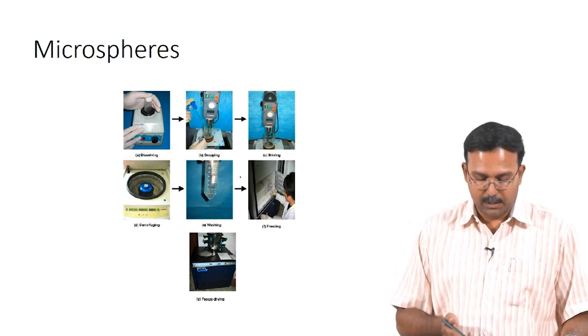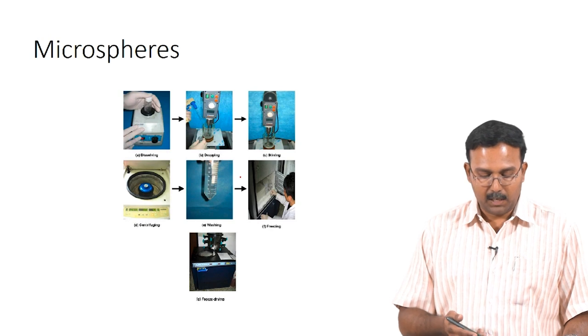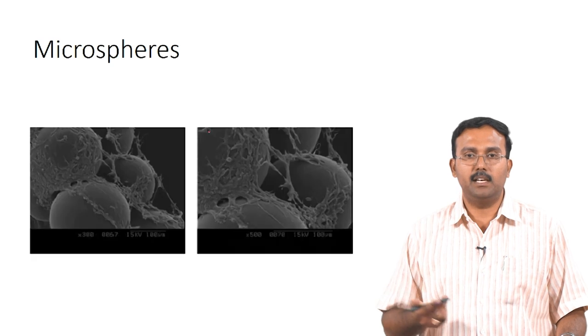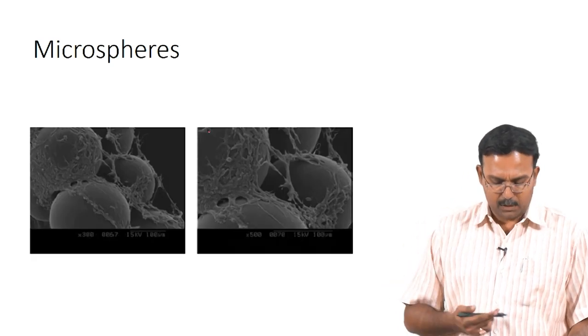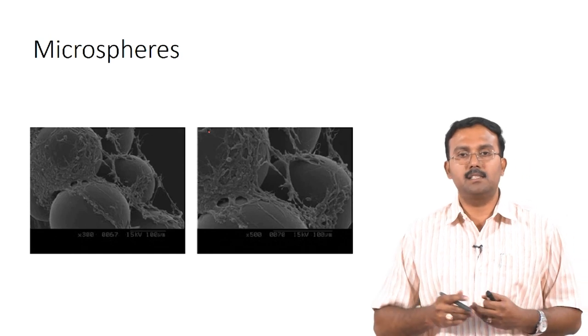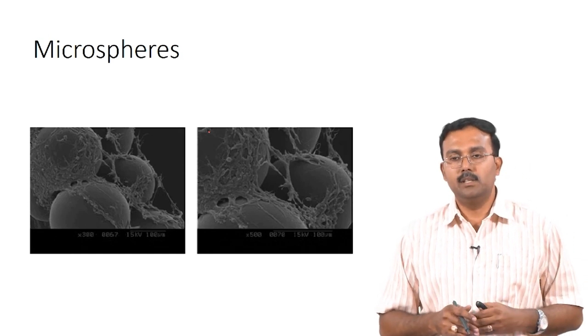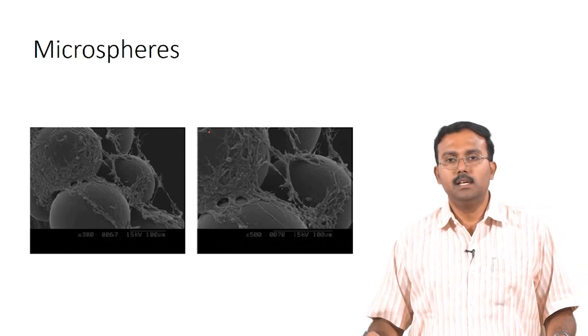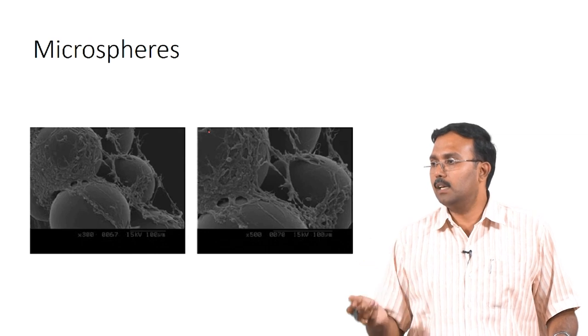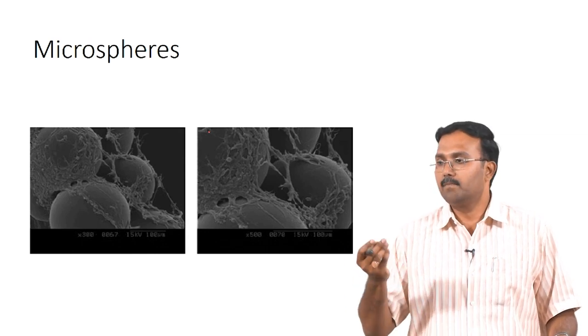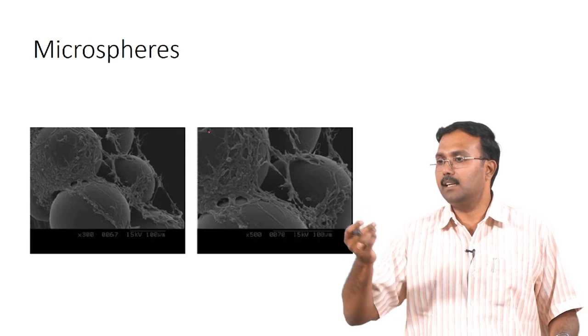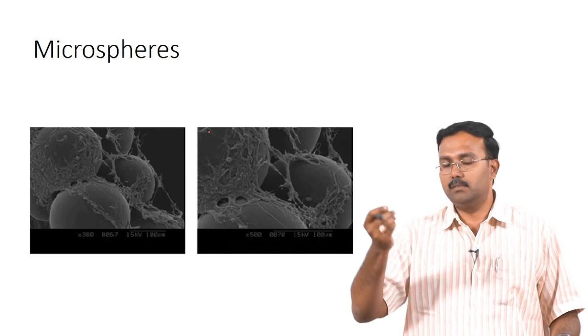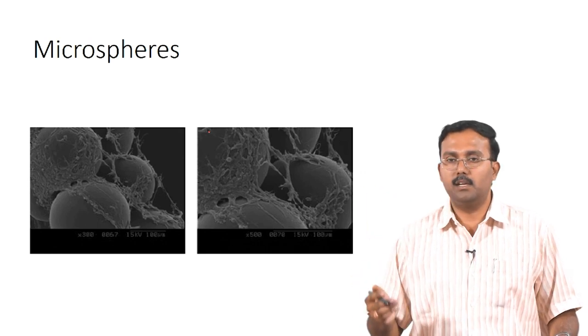Microsphere fabrication is quite simple — you drop polymer solution while a cross-linking media is spinning and you create microspheres. This shows PLGA microspheres on which human disc cells are actually cultured, demonstrating that cells can adhere. What you need to control is the viscosity of the material, the rate at which you release material into the media, and the diameter of the orifice used.